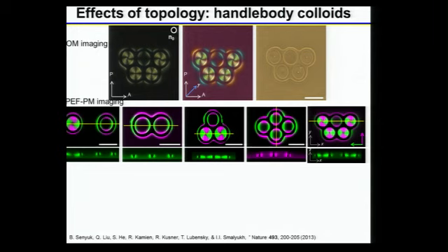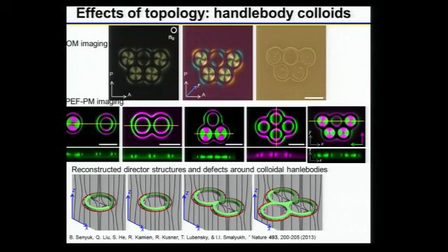So the different colors in here depict the fluorescent signals that we are getting by using different polarizations of excitation femtosecond light, which is horizontal or vertical in this case. And we can also obtain vertical cross-sections of all of those images to see what is the director structure around colloidal particles. So from those images, we can then reconstruct the details of director fields.